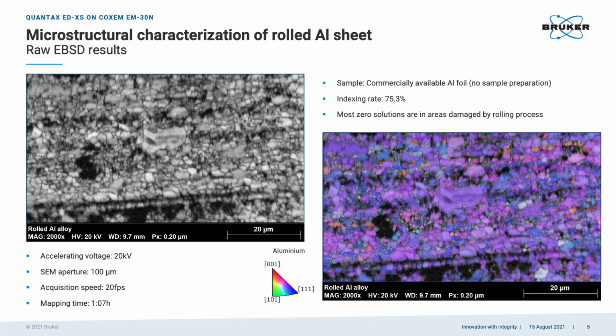You can see here what we call the pattern quality map. And you can see these parallel dark lines. These are practically defects on the foil produced by the rolling process, which is how the foil is obtained from aluminum slabs. And here is the orientation map, where we can see that the grains, the crystals in the aluminum foil have a preferred orientation.